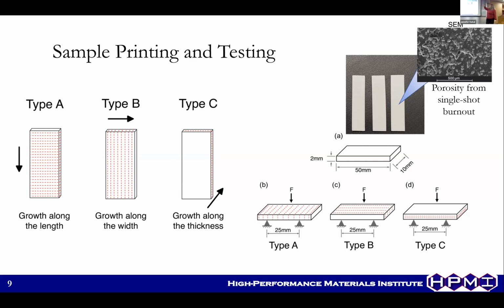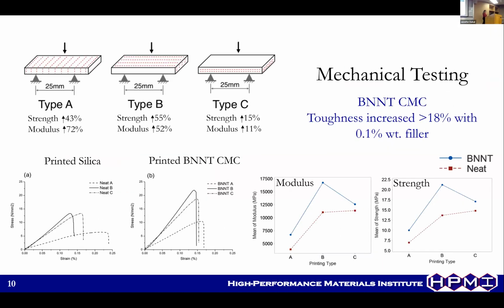So here's our porosity. You can see that it clearly has some porosity from single-shot burnout. Traditional ceramics are done through more reinfiltrations and additional sintering cycles, so that can be done. Overall, the mechanical testing showed that the toughness increased about 18% with only 0.1% weight filler. This is not terribly surprising because we have these very long, high aspect ratio fillers, and we saw that toughening mechanism between that bridging, which we'll see as we further do this investigation.